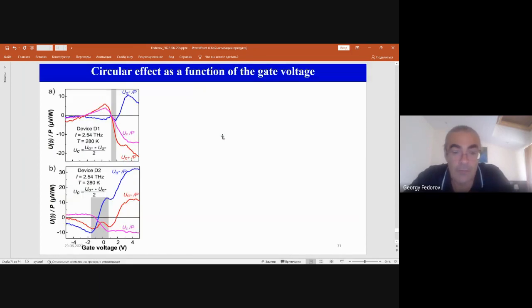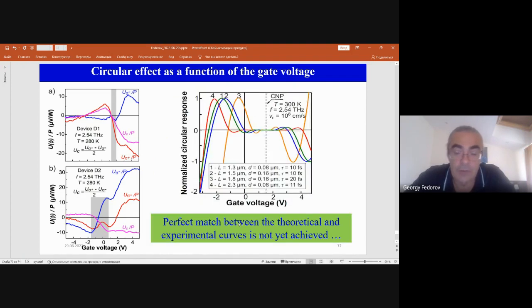So as a function of gate voltage, our effect is mostly pronounced at positive gate voltages, and it's the result of some parasitic asymmetry of the structure. So theory predicts pretty symmetric behavior. And what's more interesting, this theory predicts that the circular response should go to zero each time you have a standing wave inside the channel. So it may be a more handy way to probe these standing waves if we work with a higher mobility device, or maybe in different conditions. We can see it in CVD graphene by tailoring the channel length, frequency, and other parameters. Nevertheless, seeing these zeros is still to be done, and it is of great importance.